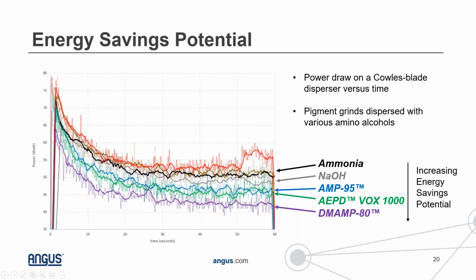The data in black is looking at an ammonia neutralized system, whereas the data in gray is a sodium hydroxide neutralized system. But if you take a look at these other curves, either the blue, which is AMP95, green, AEPD, or purple, which is DMAMP, you start to see that the power draw on this Cowles disperser is lower. So there's actually a potential to save energy by between 10 to 20%. This can really add up if you're making multiple different batches of grinds and spending a lot of time doing this in your production.